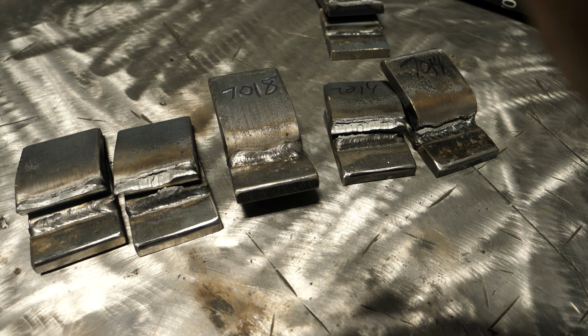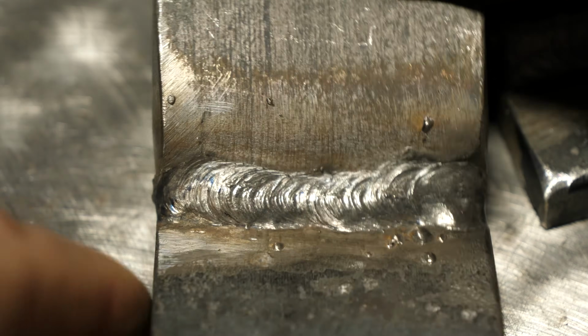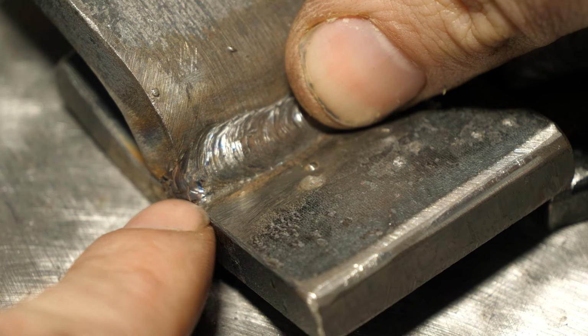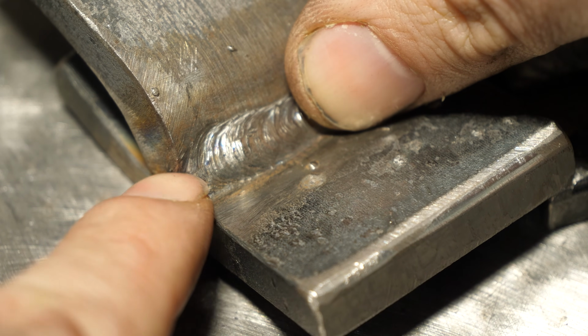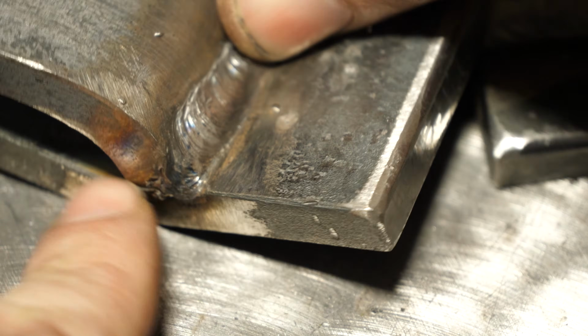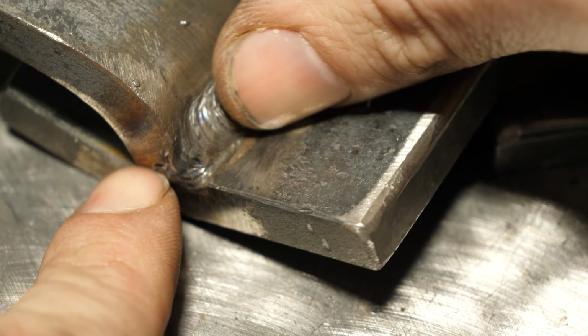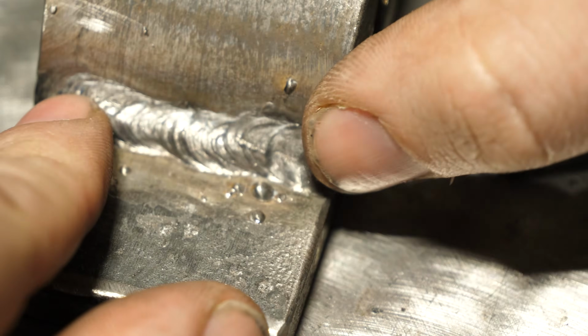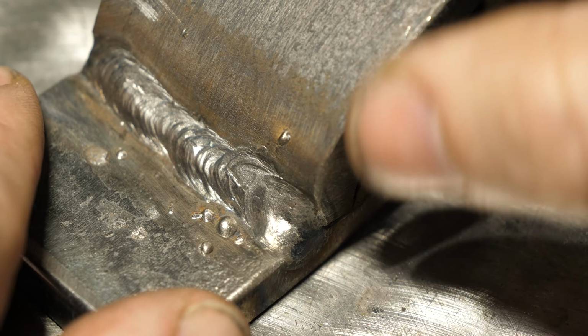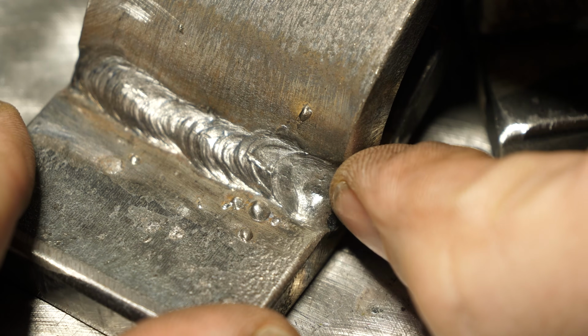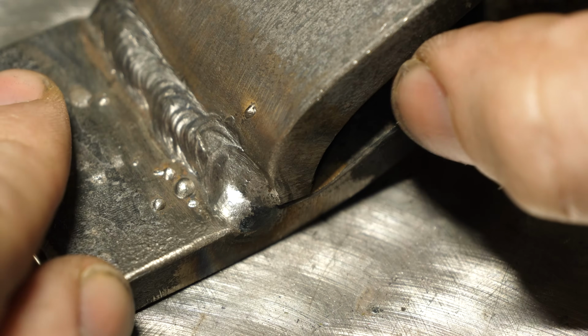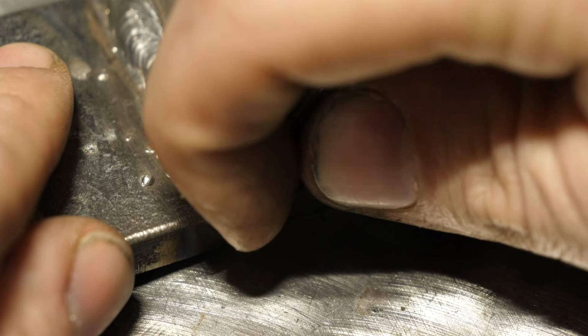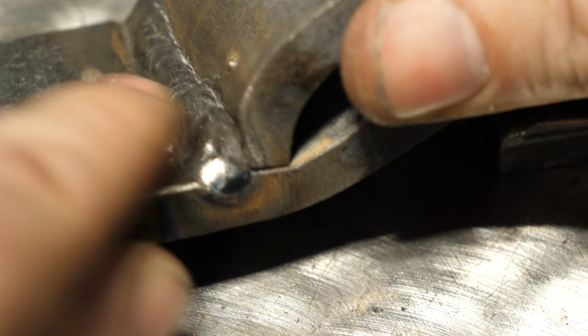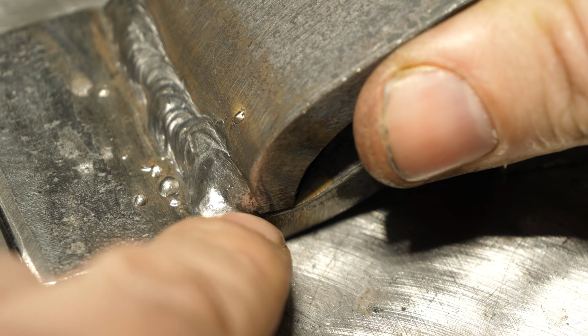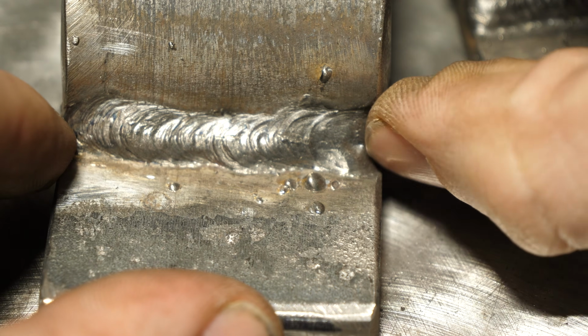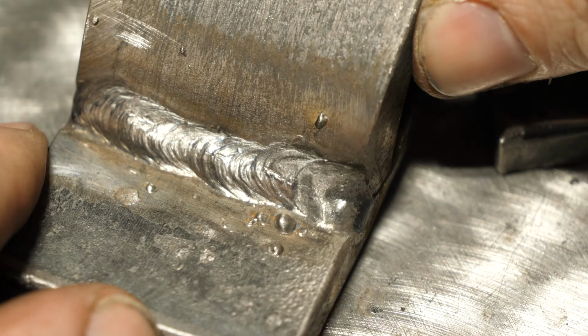And let me show you something else. What kind of amazes me is this is a 7018 weld. I have virtually no weld deposit here, like I screwed up and, you know, no weld there, very minimal thickness. The end of this is, I would say, blown out as bad, if not more, than the 7024 rods. I mean, look how thin that is there. Very thin in that section on both of them. And this still didn't fail, nor has any of them.